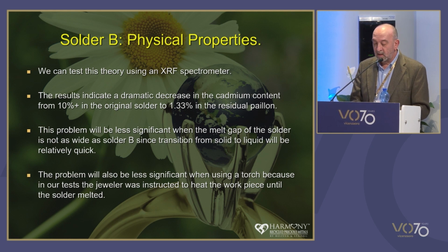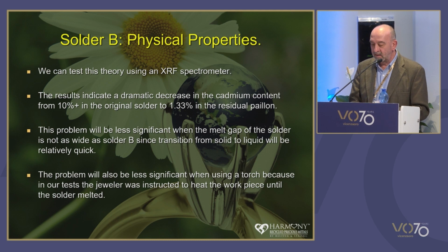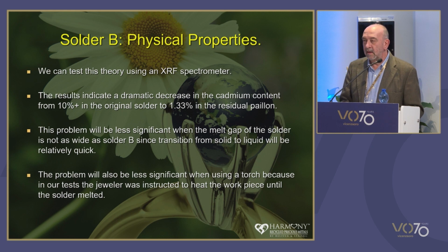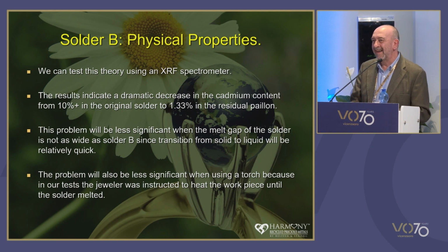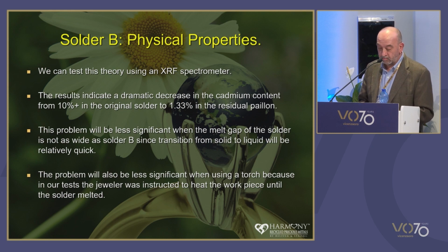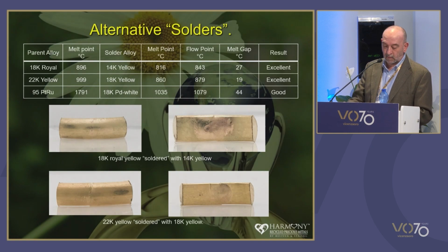So to test this, we took combinations of standard jewelry alloys and put these through the ring sizing tests. The tests were performed using the jeweler's torch only on this because the melting range of the standard alloys that we were using was actually too high for our solder furnaces. And we got some good results.